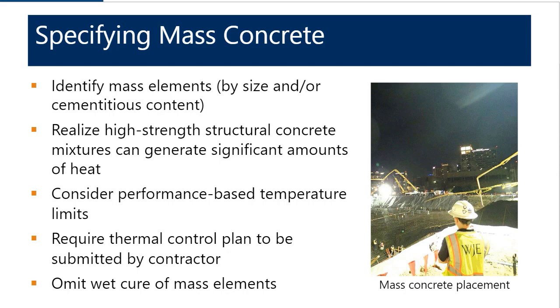If you're a specifier and you think you have mass elements on your project, one of the easiest things to do is require that the contractor submit a thermal control plan as part of the submittal process. In some cases, it might even make sense to specify that the thermal control plan be prepared by a licensed professional. As the engineer of record, that helps manage some of your risk and keeps things moving in a diligent fashion. And the final thing to think about is omitting the wet cure of mass elements, because a wet cure of mass elements can increase the risk for thermal cracking.